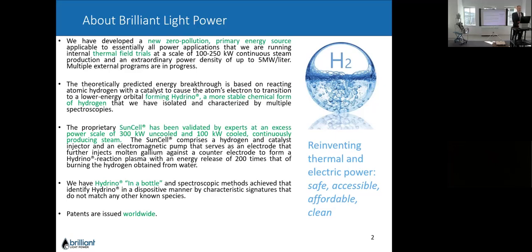It's validated at over 300,000 watts, where we heat it up without cooling, and at 100,000 watts, running it conservatively under continuously cooled steam production power conditions. The cell comprises a molten metal injector, which injects a molten gallium stream against the counter electrode to complete a circuit where we run through a high current, very low voltage to create the hydrino plasma.